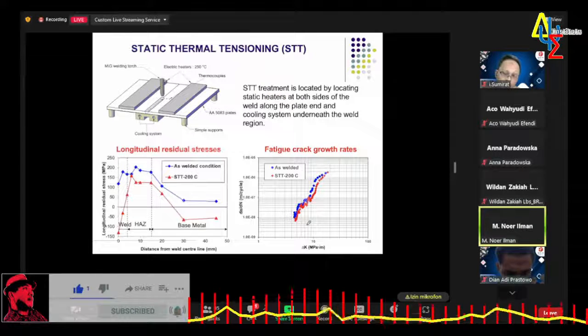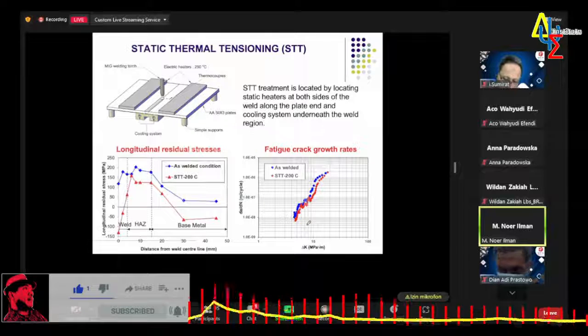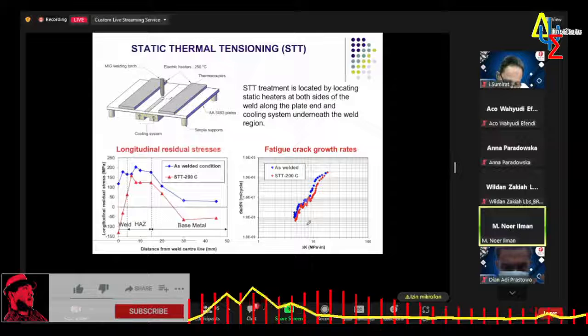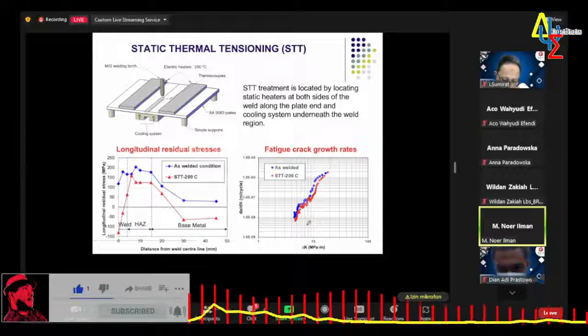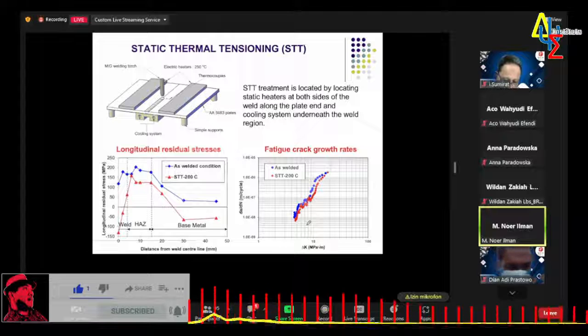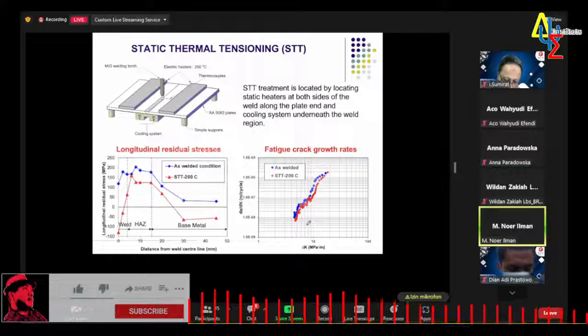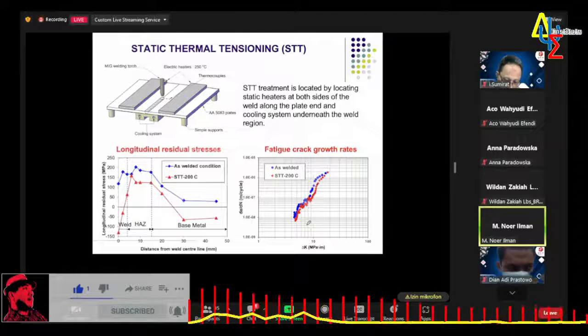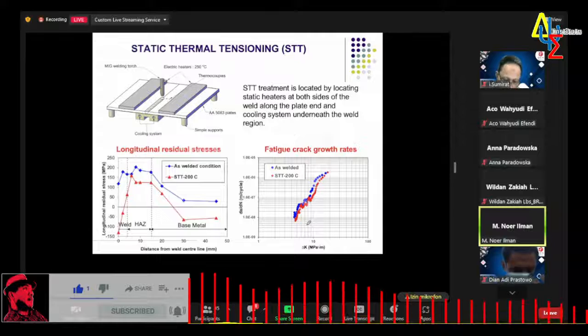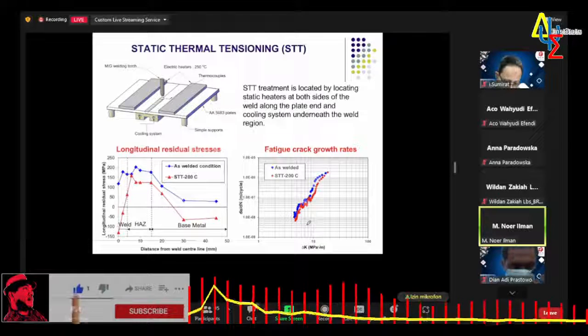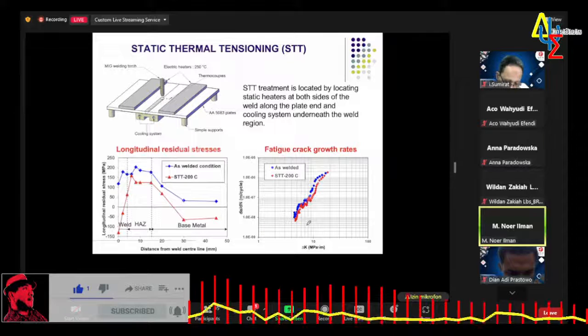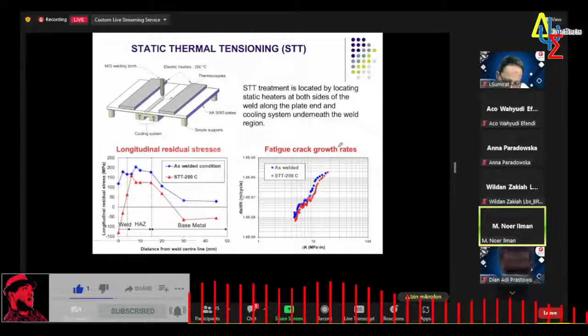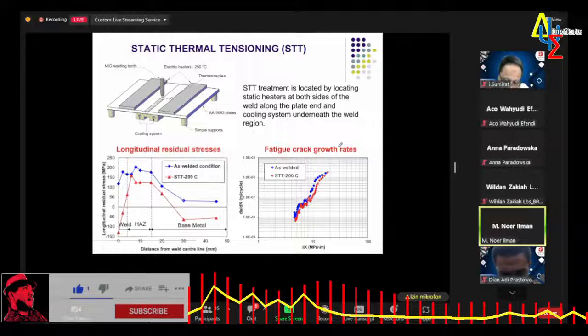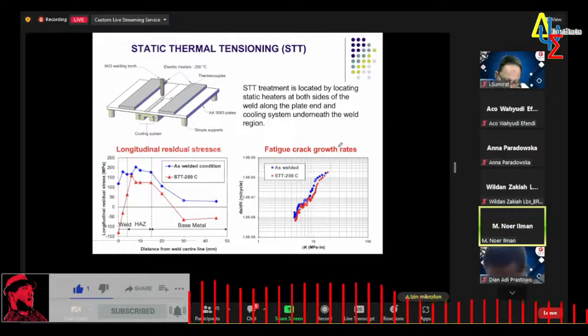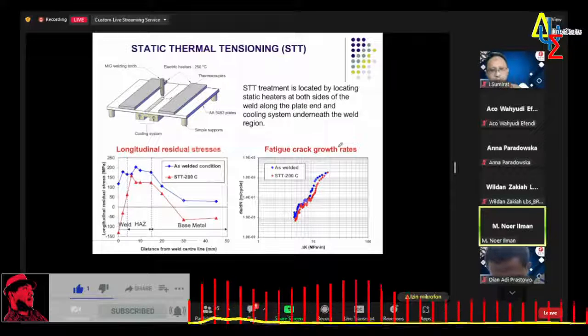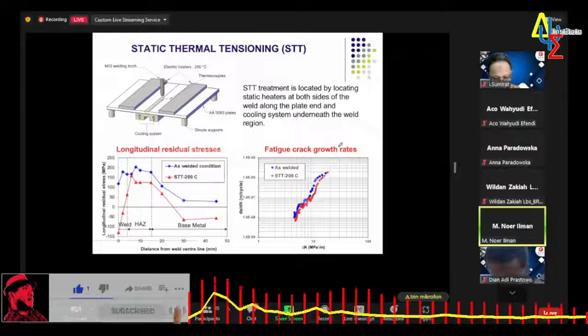So I would like to show you some results of my research, which is a collaboration between my university, UGM, Gadjah Mada University, and Batan or BRIN. First, we developed STT treatments, where this treatment is performed by locating two static heaters at both sides of the weld along the plate length. This is the plate length, and at the same time, the weld region underneath the weld region is cooled by a cooling system, which consists of water flow.